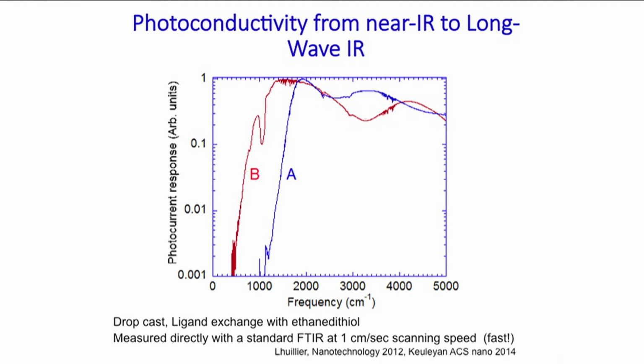And so then, with such materials, we put them onto a device, which is a set of interdigitated electrodes, very simple, and make a film of it. This is the color of such a film, semi-transparent brown color. And then we just shine light on it and measure the photo response, and they detect infrared light. So this was our first series of spectra where we changed the temperature, and you can see a small tuning with temperature, the same one we saw with the photoluminescence, and they respond.